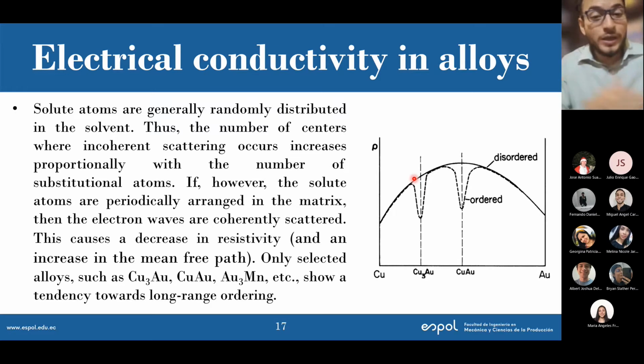And this also answers, I guess, part of your question, Fernando, when you asked, is there a way to decrease the resistivity? Well, to decrease up to the point of going lower than the actual metal, no. But at least I can go near that resistivity if I get an ordered microstructure. And you can see when it's ordered, there is actually a decrease in resistivity, right? It deviates from that disordered state that would predict an increase in resistivity. It actually deviates because I have an ordered microstructure.